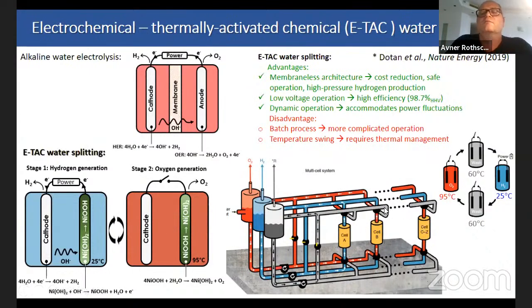In an industrial process, we have multiple cells, and each and every one of these cells go through this cycle that is shown here. First, at low temperature, we connect it to a power source, and then we have hydrogen evolution at the cathode while the anode is being charged. Then we introduce an intermediate temperature electrolyte simply to wash the cells, to wash the remaining of the hydrogen from the cell. And then we introduce the high temperature electrolyte that induces this spontaneous oxygen reaction, and so on and so forth.